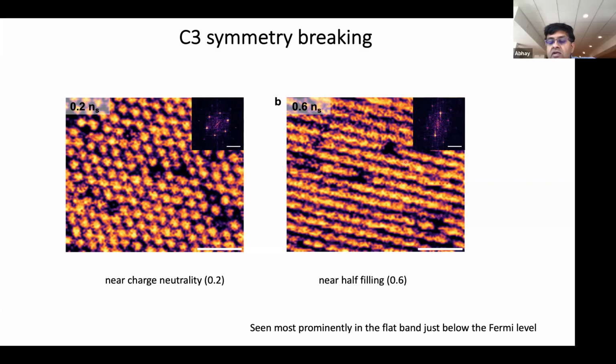So the twisted bilayer, to be honest, the size over which we can get strain-free areas is so limited that I wouldn't be able to give you a good answer to that question. But you cannot look at different parts of the same sample and just see which way it's oriented. It does, but the strain also varies significantly on that same length scale. And so it's very difficult to tell. So the answer is not particularly meaningful in that case because of the strain. That's right. And I don't think anybody has a good answer there as of now.